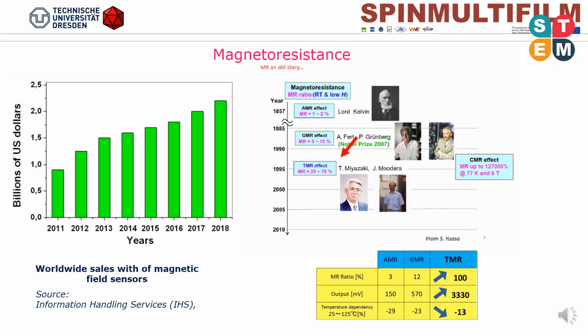The tunneling magnetoresistance TMR, a magnetoresistive effect that occurs in a magnetic tunnel junction consisting of two ferromagnets separated by a thin insulator, and the colossal magnetoresistance CMR, discovered in 1993, a property of some materials, mostly manganese-based perovskite oxides, that enables them to dramatically change their electrical resistance in the presence of a magnetic field. The CMR effect in both bulk and thin films always needs a large magnetic field, which limits its application in spintronic devices. On the other hand, the TMR effect is the most sensitive magnetoresistive effect at room temperature.